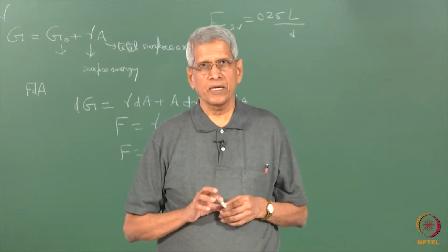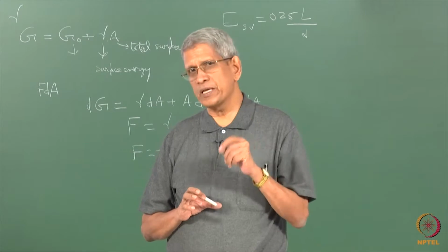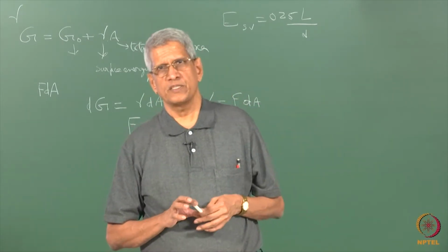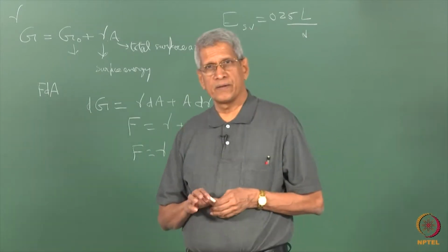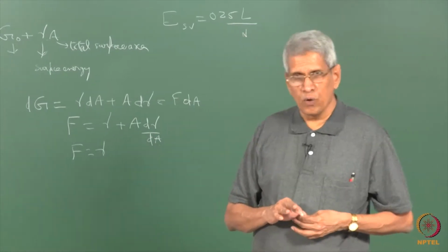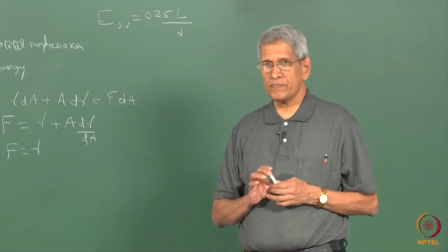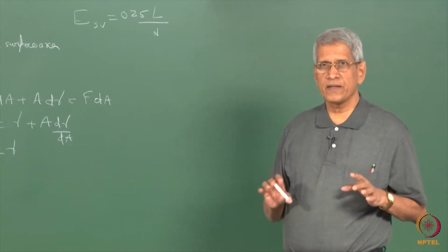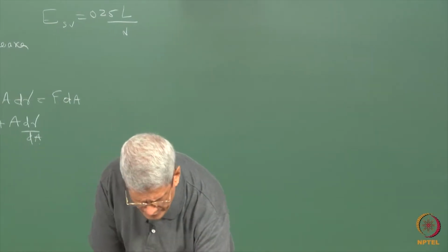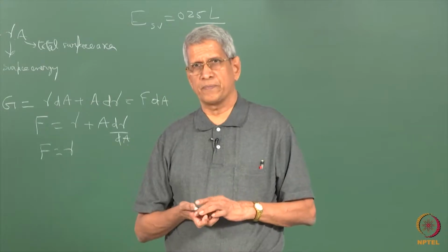So, that means that depending upon the number of bonds to be broken, which is going to change depending upon the nature of the surface, the surface energy will change, correct. Close packed plane will have the lowest surface energy. Is this clear? Okay. Then this energy which we talk about is the surface energy.